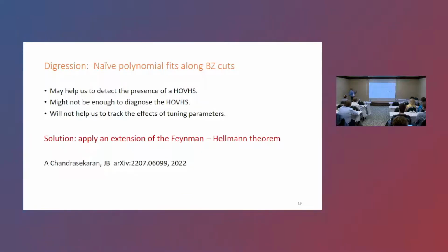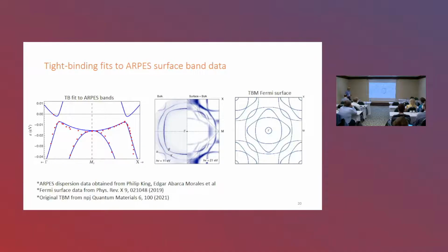Now, a small digression, because we wanted to use the input from both experiments to give a final answer, but polynomial fits along Brillouin zone cuts may not help due to various reasons. It might not be enough to diagnose a higher order singularity, and also what you ideally would like is to start tuning this, and this does not help us to track the effect of tuning parameters. So in recent work, we applied an extension of the Feynman-Hellmann theorem for multi-band systems to get the right tools to be able to analyze this type of singularities.